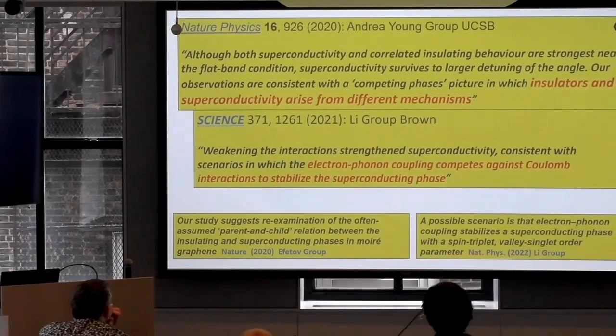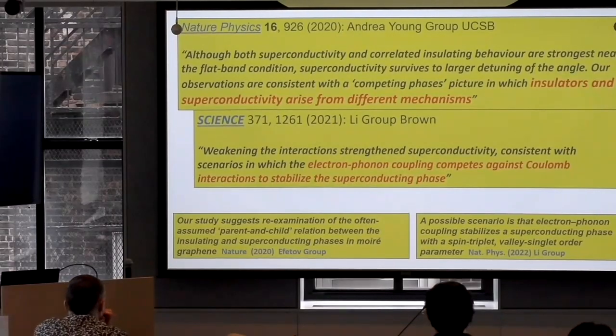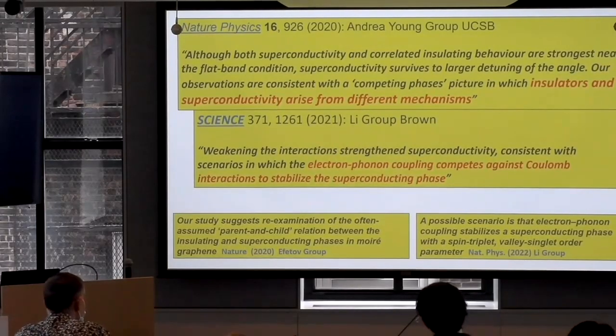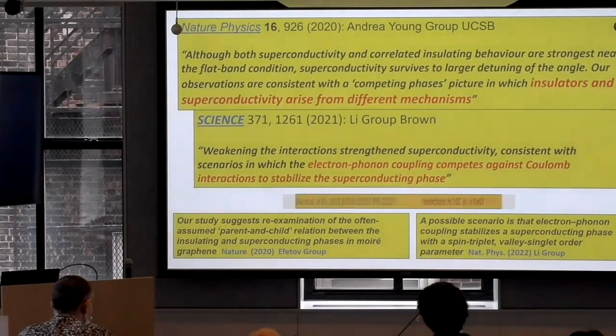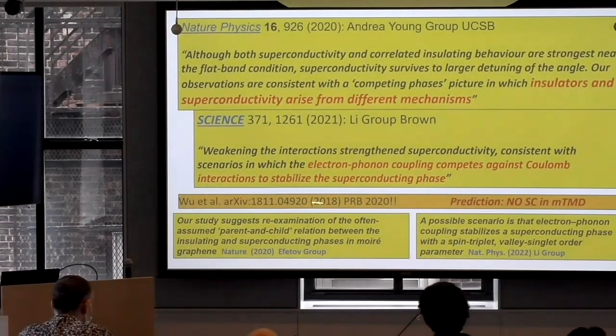There are also papers from the Li group, Nature Physics, saying a possible scenario that electron-phonon coupling stabilizes superconducting phase with a spin triplet valley singlet order parameter. This is what we said could happen. People originally thought you cannot get triplet superconductivity in the spin channel from electron-phonon, but here you can. So our paper was posted long before.